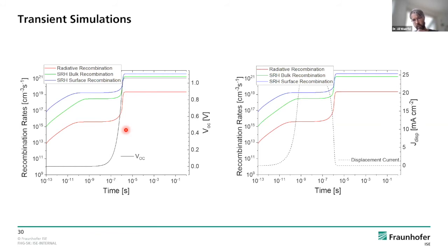You need charge pairs to really separate, and they flow towards the electrodes. Yeah? Either until they are at the surface of the electrode or a bit before. I will show you a slide later on. But you need this kind of separation of charge pairs in order to charge your capacitance. And the nice thing is, if you look at this slide here, this is the displacement current, where you can see that during this time where the recombination rates are surprisingly constant, you have a large rise in displacement current. This displacement current means you charge the electrodes, and this gives rise to the very steep open circuit voltage increase, after which everything is constant, and you can see the displacement current going back to 0. So this is then the steady state situation where we don't have any displacement current.